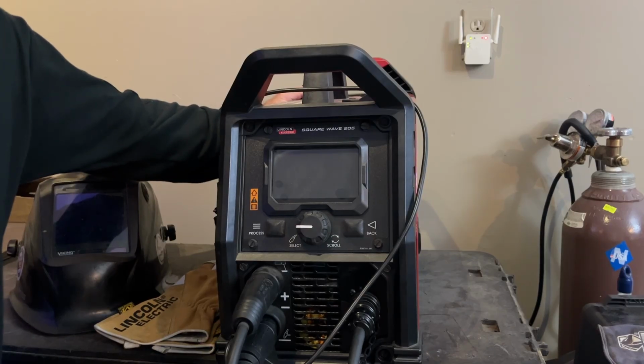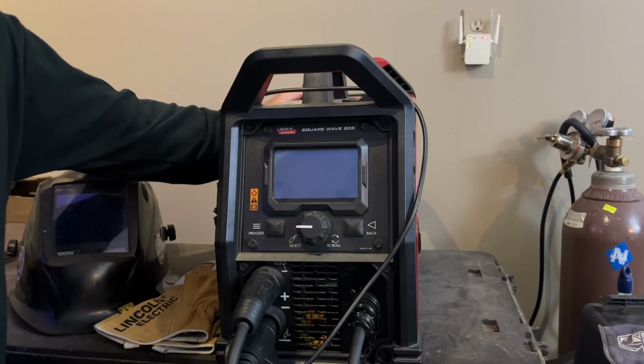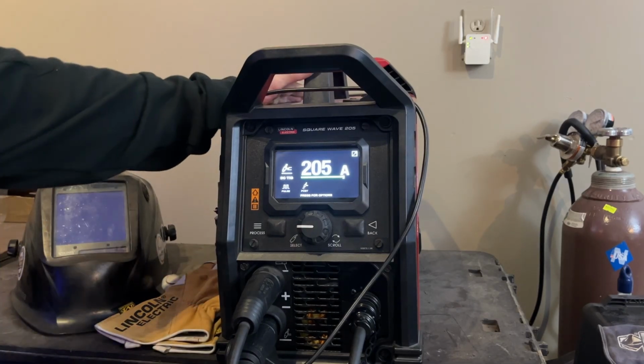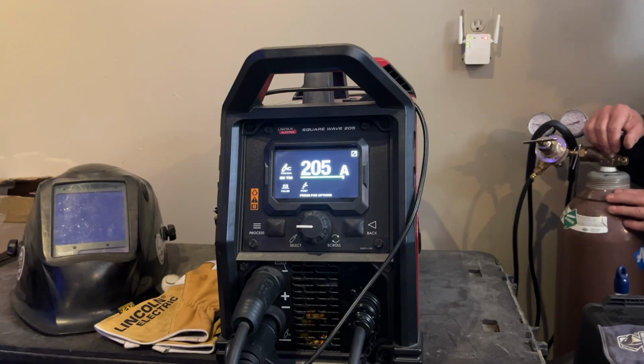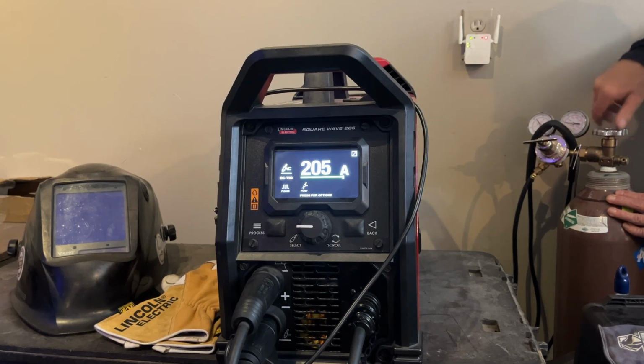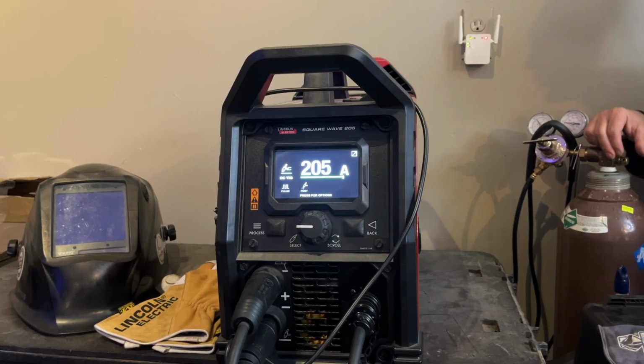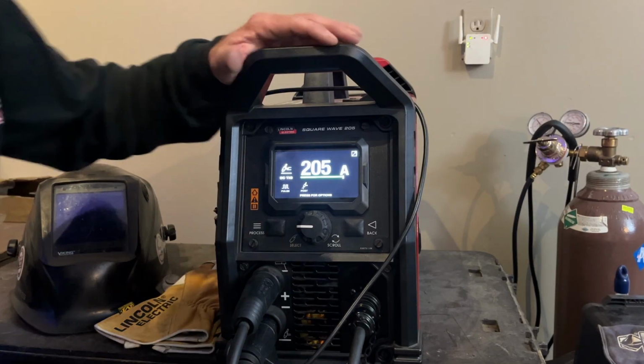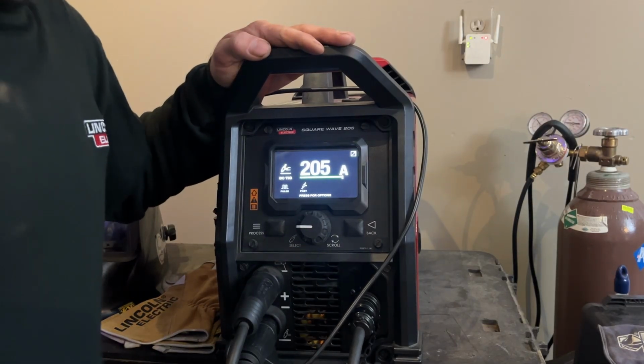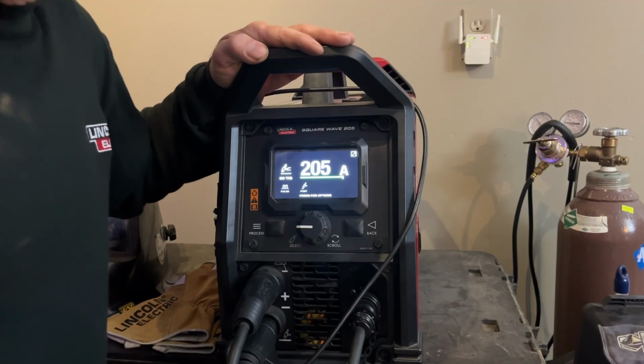All right, let's set up for welding aluminum today. In this case, I'm running 100% argon shielding gas. You could mix a little helium with it. Helium increases the arc voltage at the same output current. So by doing so, it increases the arc energy, and it actually can help aluminum melt just a little bit quicker. Helium also slows the cooling rate, so welds made with helium are less likely to have porosity.